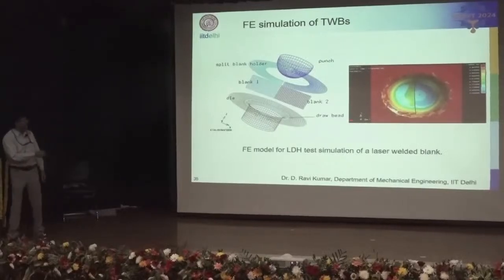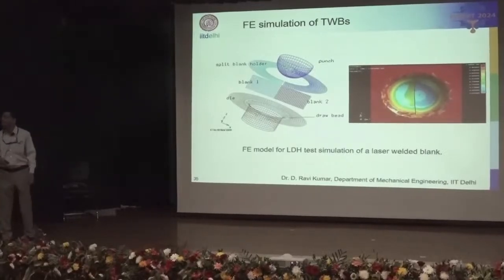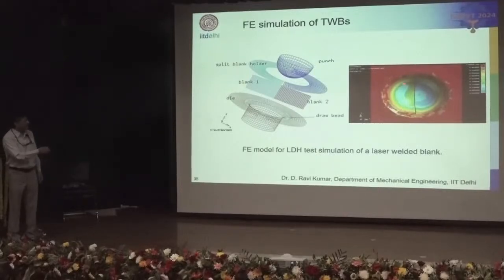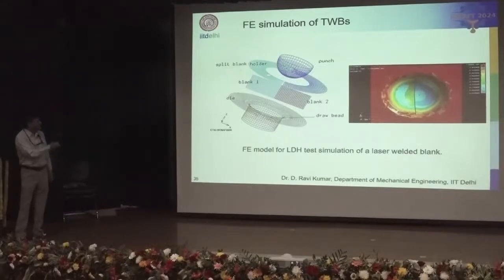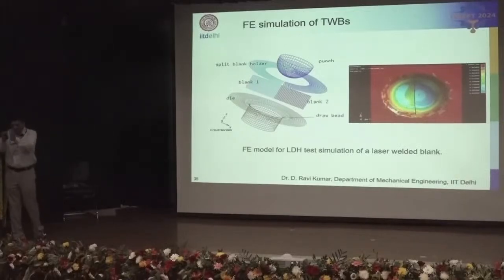Here you can see the finite element simulation of a limiting dome height test for a Tailor welded blank. On one side you have one kind of strain distribution, on the other side a completely different kind of strain distribution. When you define the material model, you need to define three material models: for parent material 1, parent material 2, and for the welded region. So it is important to determine the properties of the welded region also, so that our simulations are more accurate.